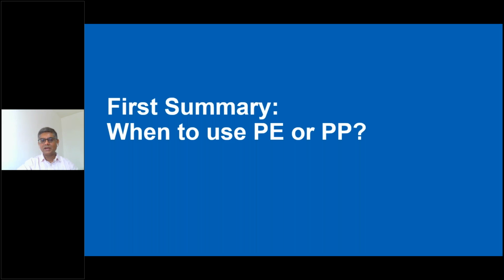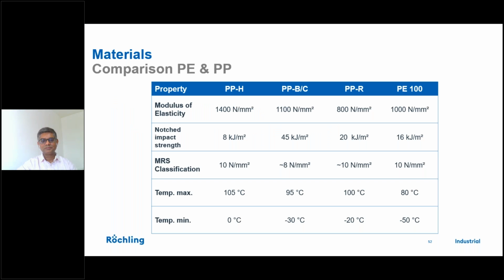Okay, so many a time people will ask what to use, which should be our first choice of selection, whether it is polyethylene or polypropylene. So here are some ready reckoners. There is a comparison here: PPH, PPB, PPR, and PE100. I can tell you that most of the time for Indian conditions, people generally go with PPH, because it has a nice temperature range from 0 to 105 degrees Celsius. PE can be used when you have sub-zero applications. Again, 80 is the maximum, but generally HDPE works very well up to 60 degrees Celsius.